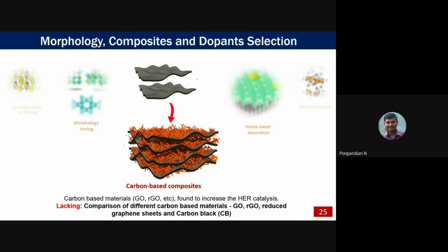Now, what we are doing is making the composite with that particular tungsten oxide, adding graphene to the tungsten oxide. Here we have used 2 different graphene oxides. One is a general graphene oxide, another one is a reduced graphene oxide, to make the composite. In that way also we are improving the efficiency of that nanomaterial.